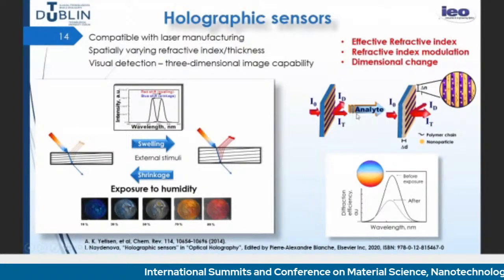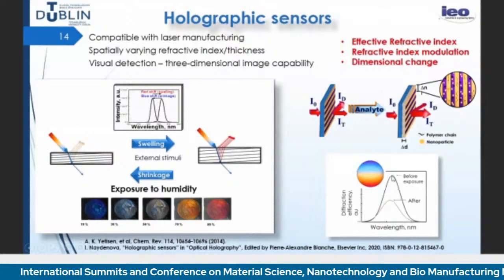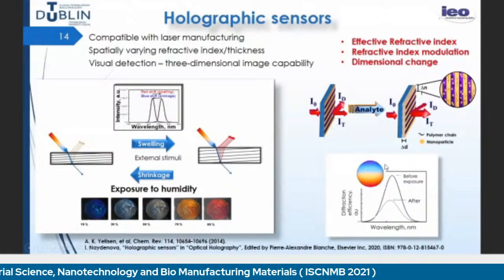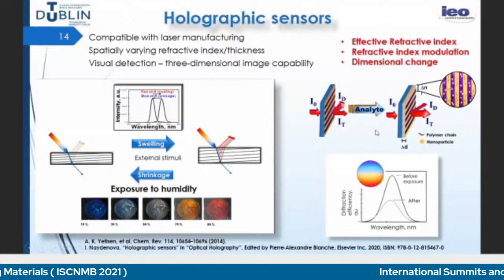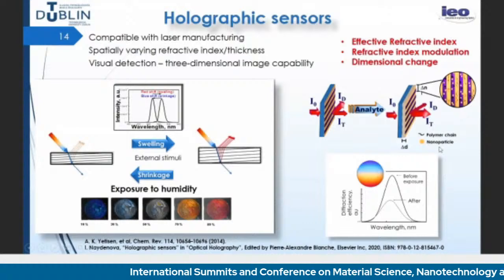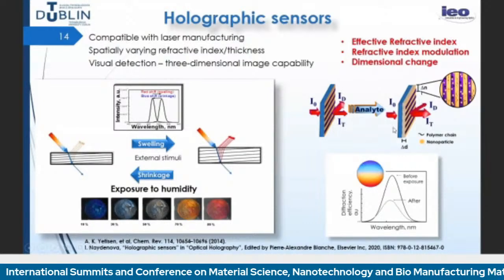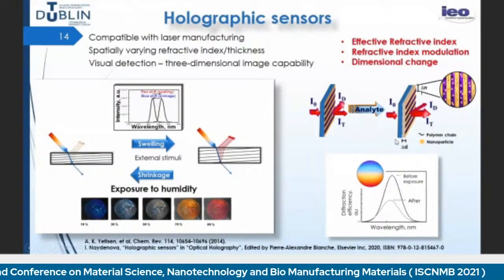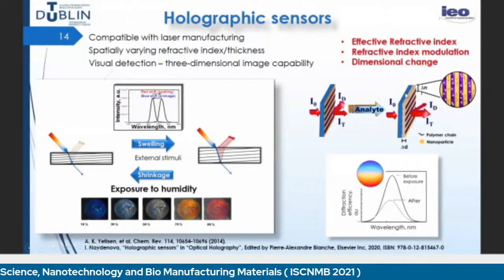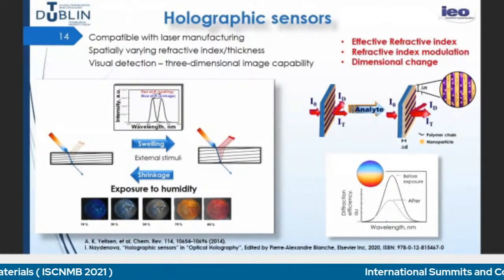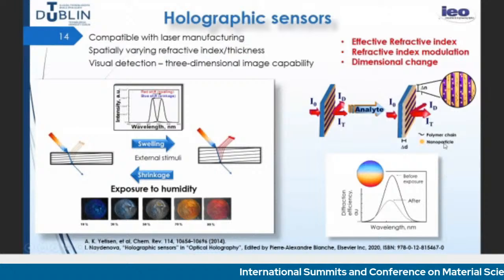In transmission mode, because the gratings typically diffract, they are much less wavelength selective. They diffract multiple colors, and you can observe them from different angles. So in this case, visual indication is not very practical, not very accurate. So what we do is measure the diffraction efficiency. The diffraction efficiency depends on a number of parameters, especially the refractive index modulation, and it can change when the analyte is absorbed, preferably in bright or dark fringes. And I'll explain how we can use the zeolite nanoparticles then.